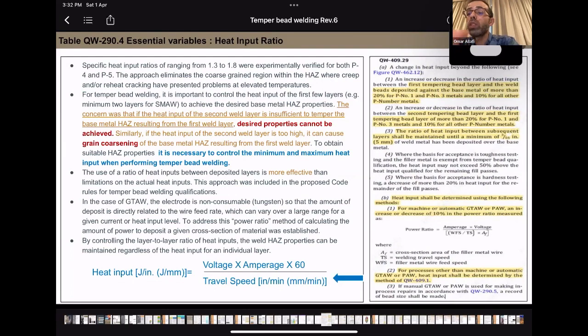So what is the issue of GTAW as a technique? In SMAW you have this formula for calculating heat input, which is voltage multiplied by amperage multiplied by 60 over the travel speed. But you cannot calculate the heat input or the ratio using the same formula in GTAW. What you need to have is a power ratio.